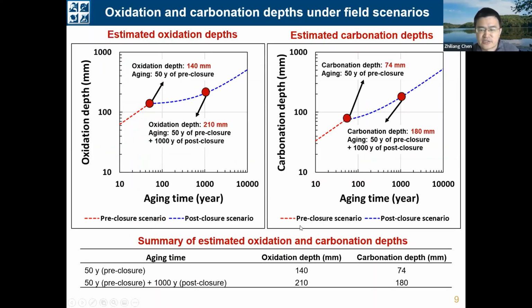So with the above aging time frames and the aging conditions, we can use the aging model to estimate the variation of the oxidation and carbonation depths along with the aging times. At the bottom in this table, I summarize the oxidation and carbonation depths at the end of the pre-closure and the post-closure periods. So as you can see, a large fraction of the oxidation and carbonation happened during this pre-closure period, with a relatively short period of time, with only 50 years.